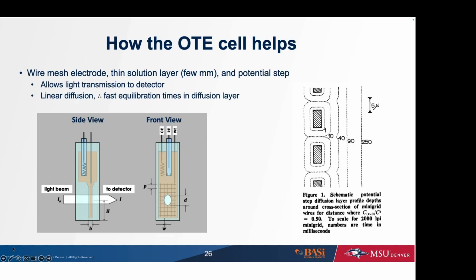Right, so that is another reason why the cell has this funny kind of bump in it. So we've got quartz over here, and then we have this very small path length. Usually we have a 1 centimeter cell. Now we go between a 2 millimeter to 5 millimeter path length to try to beat mass transport and enable our diffusion layer to be thinner than the thickness of the cell. And again, that's just to get our equilibrium to be quickly established and then pushed towards the product we want.